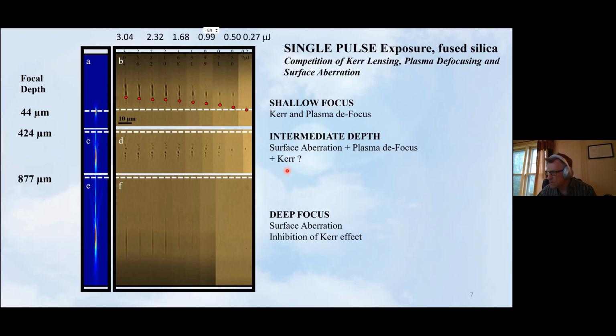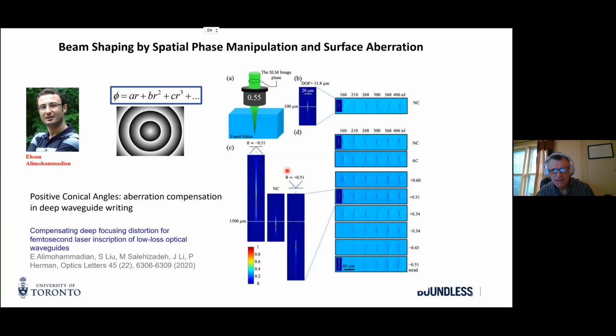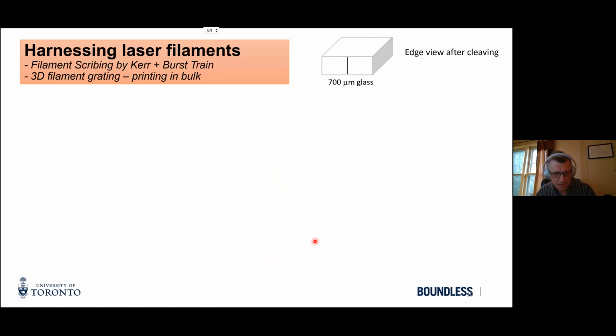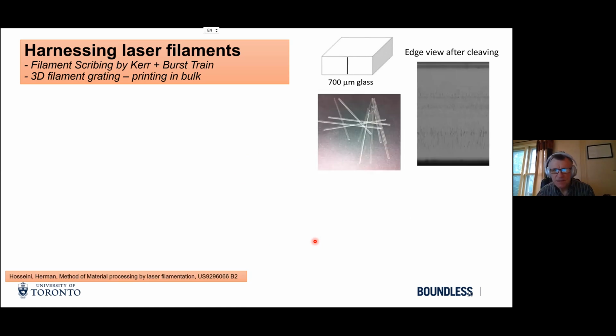And so you can see where beam shaping is really attractive if you want a flexible processing tool. And we've published a few papers in this area using the spatial light modulator, imposing phase fronts like this to make filaments. And we're making waveguides. We're doing microchannel etching with controlled shapes. And we're using filaments in a variety of ways that I will just slide into now. So, in harnessing filaments,